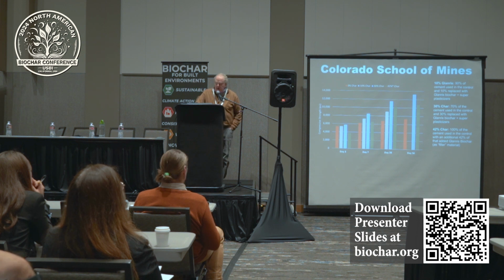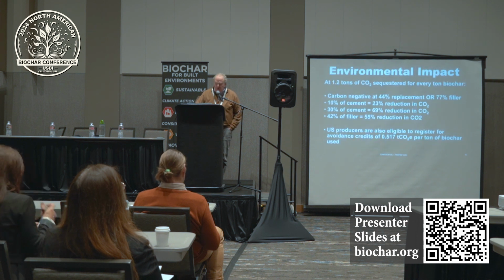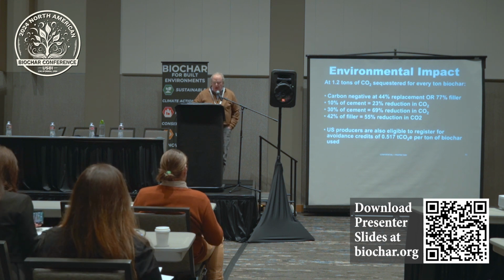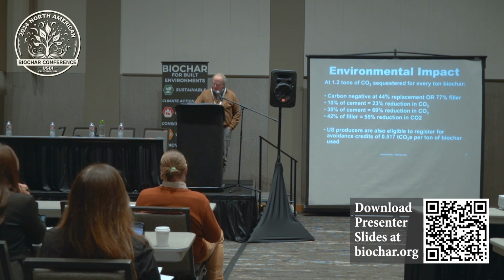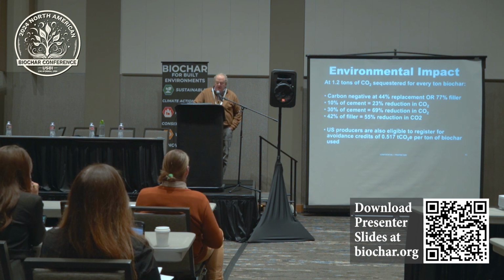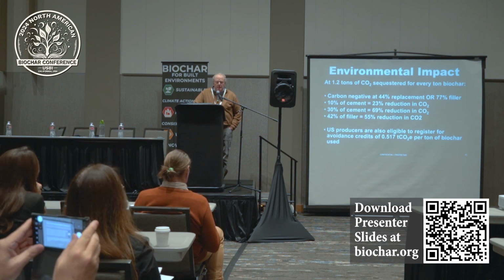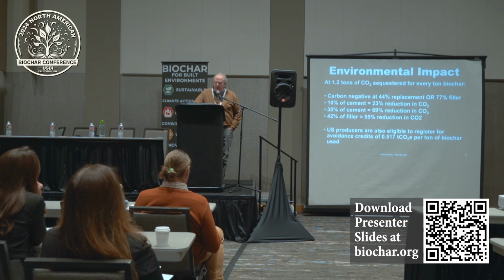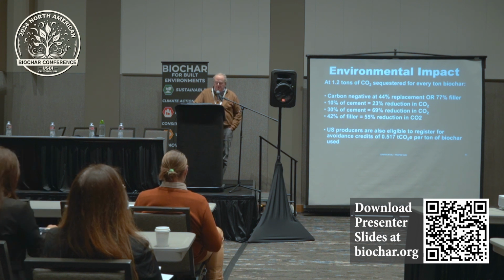They also did some studies looking at replacing the aggregate with our material, and you'll see that in the dark red. The key thing that was interesting to us, and again Lori touched on it, so sorry for the repetition, is that at about a 30% replacement of cement, at the ratios we're talking about here, you're looking at a 69% reduction in CO2. That's a pretty hefty reduction in the carbon footprint.